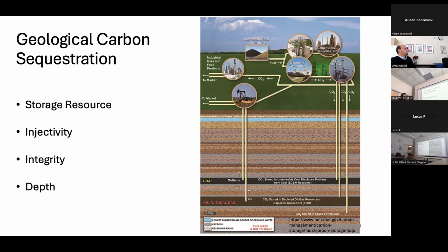And the second element is injectivity. So that's the rate of CO2 we want to inject into the subsurface. And the third is integrity. So integrity is basically a way to permanently store the CO2 in the subsurface. So a seal, or multiple seal layers of seal formations, are needed for that to happen. In this case, we have a saline aquifer, and on top of it there's a low permeability seal, so that it prevents the CO2 from migrating upward.